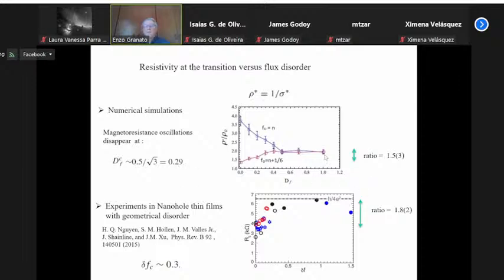And the increase of the resistivity at the transition compared with the zero disorder is very close to what we see experimentally. We find 1.8, here we find 1.5, but regarding the error, they are very close together. And so there is a good agreement between experiment and theory, showing that this modeling describes the system reasonably well.